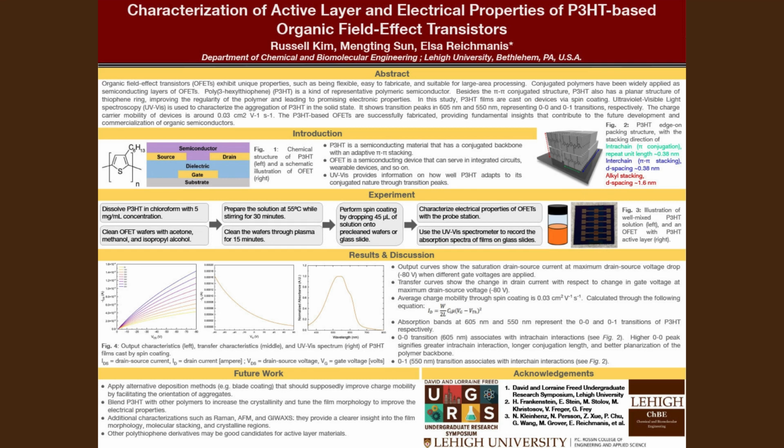For the P3HT side of the experiment, we begin by weighing solid P3HT using a weighing paper. Typically, we extract 2 to 3 milligrams of P3HT and dissolve it with chloroform at a 5 milligrams per milliliter ratio. In our case, 0.4 to 0.6 milliliters of chloroform. Because of the physical properties of the P3HT solution, such as volatility, we must use a well-sealed amber vial, where it can block light. Then, we add in a magnetic stir bar so that the solution can be mixed at 55 degrees Celsius at 650 rounds per minute. To prepare a well-mixed solution, 30 minutes of stirring is recommended.